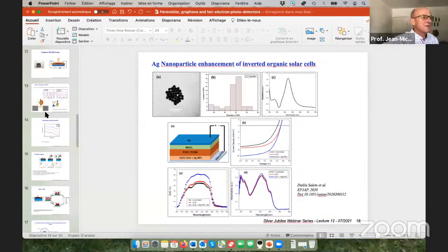Thank you. The field effect transistor is a good way to measure that, because you go from the hole to the electron transport regime, and the minimum is shifted by both the nanoparticles and the light. The nanoparticles shift it, and then the light can shift it back and forth as well. So this is a way to detect how many eVs you have, and the range is like 0.1, maybe 0.2. Thank you. I didn't show this data, but maybe in the next lecture I will show that. Sure, this gives the result you are asking for.